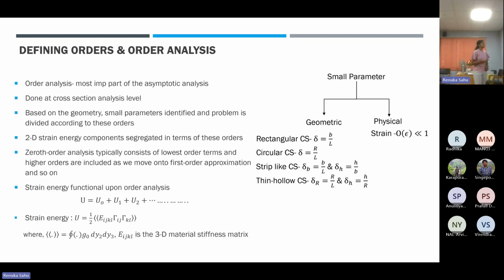So the 2D strain energy components are segregated in terms of these orders, and the zeroth order analysis is done. When you get the strain energy in terms of these orders, you can summarize it as U equals U0 plus U1 plus U2, where U0 considers the lowest order terms in the strain energy. For zeroth order, this is only minimized.